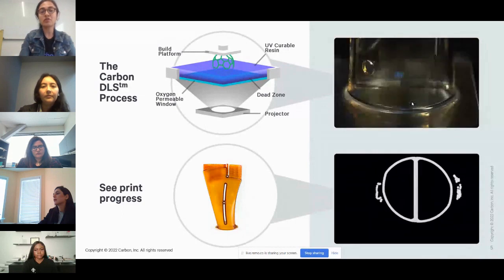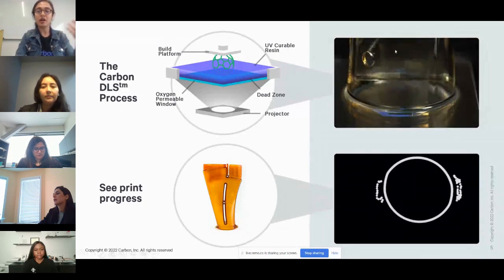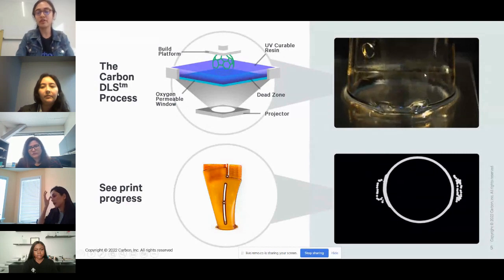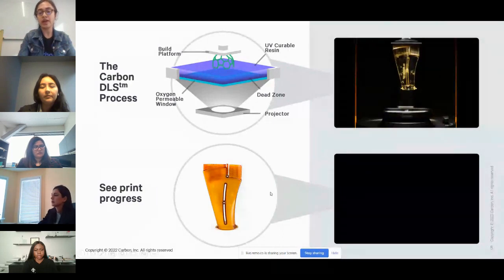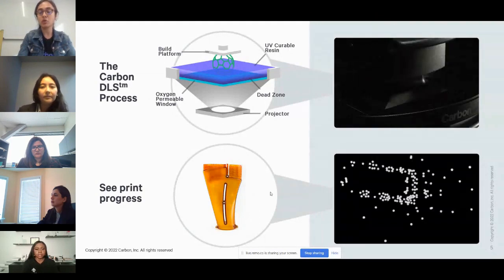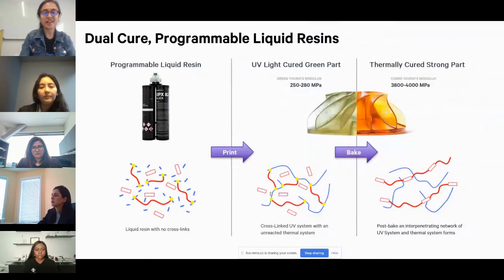One of the unique features of our technology is that we take out this green part, which has been 3D printed, and then it's baked in an oven. Then it's thermally cured, and finally we get this 3D printed part, which has unique mechanical properties. It's strong, it's tough, it's durable, it has good surface finish, and also isotropic mechanical properties. A little bit more on the technical side of things: I won't go into too many details, but again, one of the unique features of the technology are these dual cure programmable liquid polymer resins.